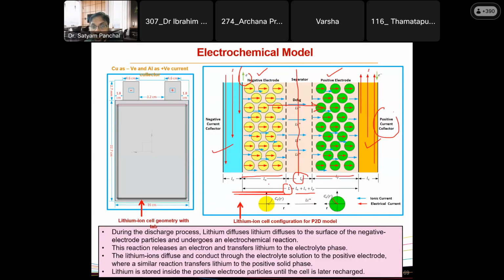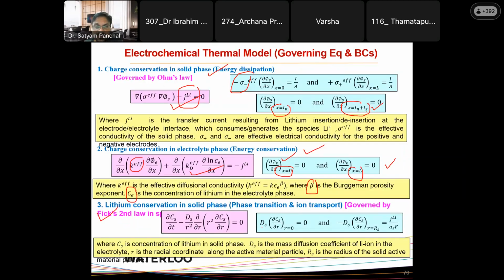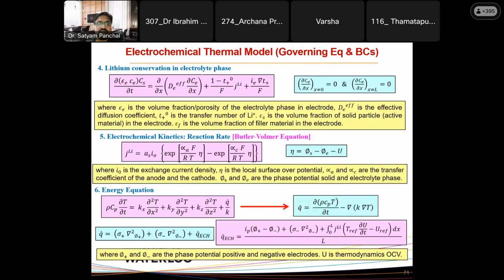So in spherical coordinates, in this direction, it is given by this equation, where at radius r equal to 0 and radius r equal to rs, those boundary conditions are provided. Cs is the concentration of lithium in solid phase, and C is the concentration of lithium in the electrolyte phase. Ds is the mass diffusion coefficient, r is the radial coordinate along the active material, and rs is the radius. In the same way, the electrolyte phase equation is provided over here, and at x equal to 0 and at x equal to L, boundary conditions are provided, where t plus 0 is the transfer number of lithium, and epsilon s is the volume fraction for solid particle, and epsilon f is the volume fraction for filler material.